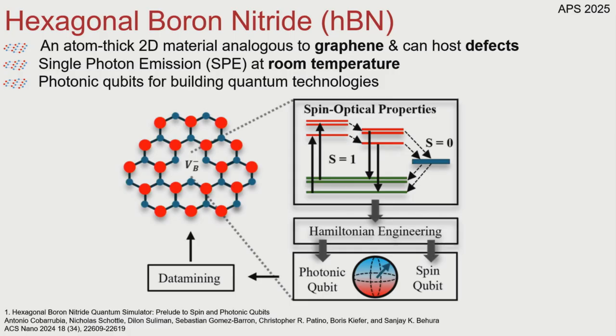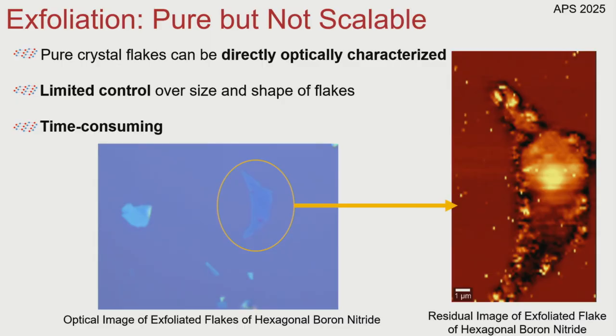Now, first, you actually need to readily produce hexagonal boron nitride in a scalable and replicable way. Now, most labs, as I've seen in other presentations here, utilize exfoliation, where you take a bulk crystal of hexagonal boron nitride, you apply Scotch tape, you peel it off carefully, and then you peel, and you peel, and you peel to get down to a monolayer.